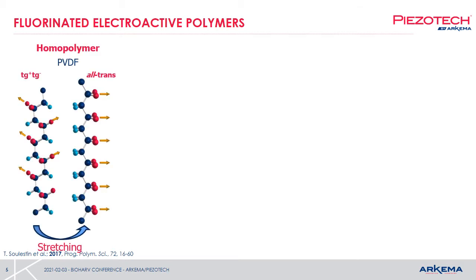So we have a large range of fluorinated electroactive polymers. As I said, the first one is PVDF. PVDF homopolymer is a linear polymer with an alternating CH2, CF2, CH2, CF2 chain structure. You always have some defects, but let's stick to this one. And this polymer is going to crystallize directly from the melt in a trans-gauche conformation leading to an alpha phase. If you want to have the all-trans conformation and the beta phase, this transformation will later give the piezoelectric properties because you have all the dipoles aligned in the same direction.